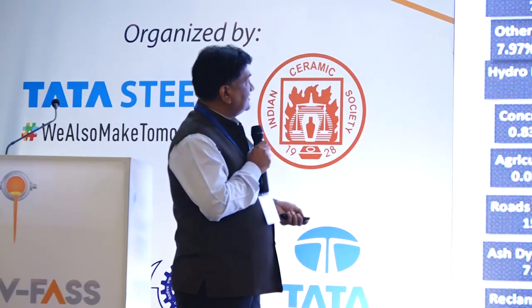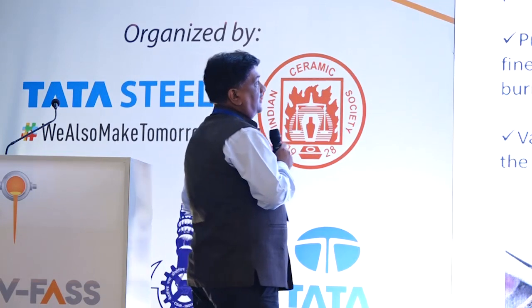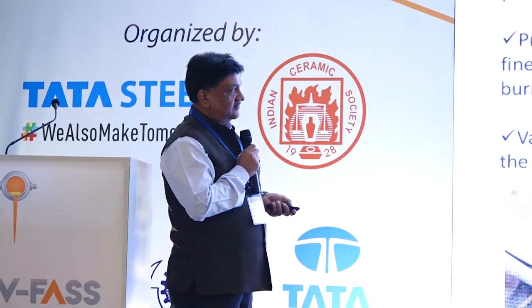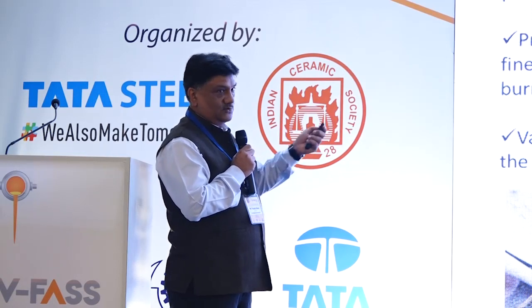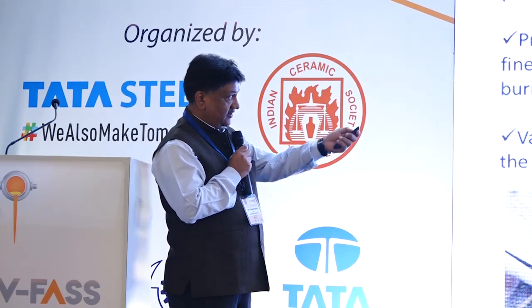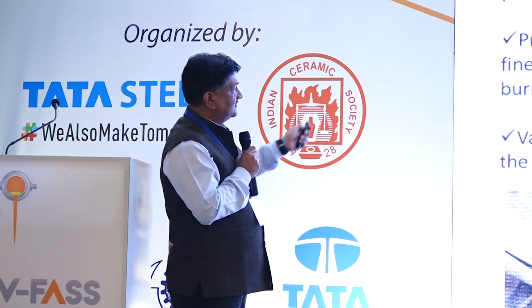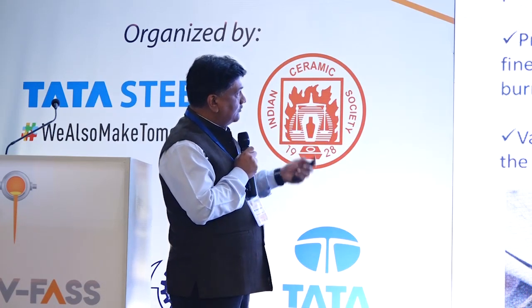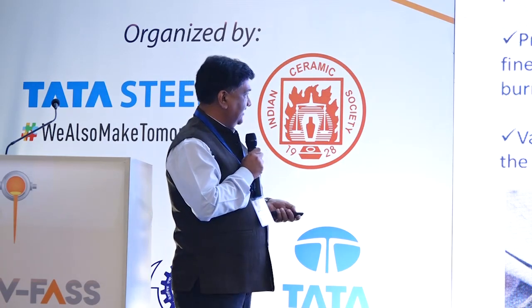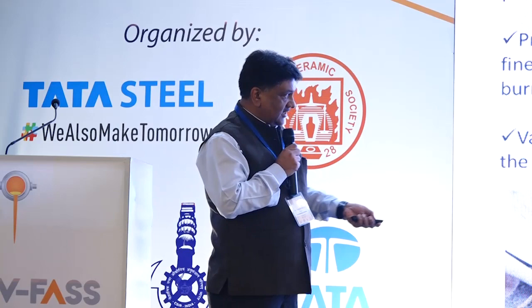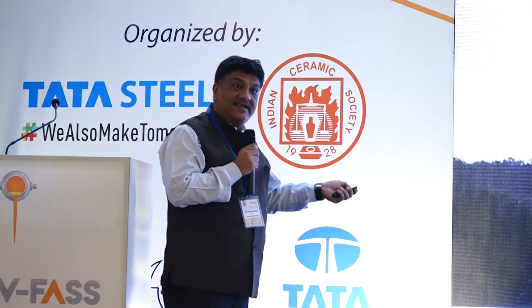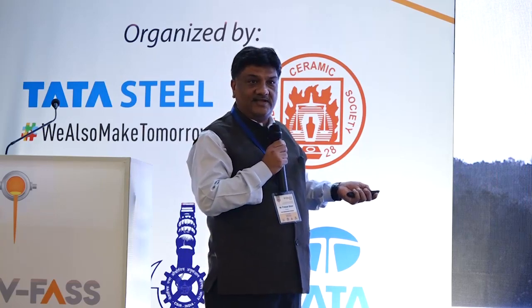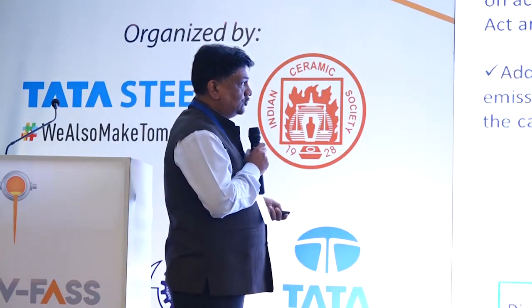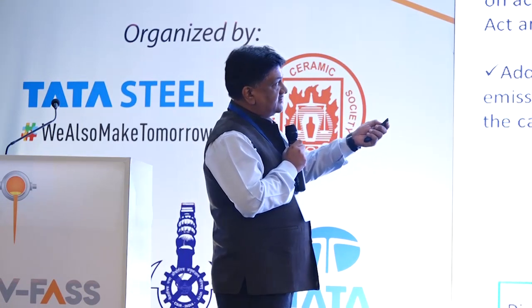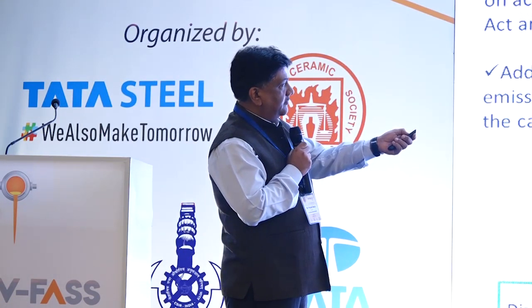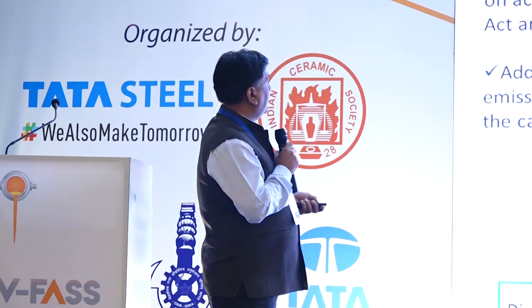So these are statistics on Indian industry. What majorly affects utilization of this combustion product? Of course, the sulfur, free lime, which has been talked about, unburned carbon, and gradation and collection process. So this is a function of all these factors which is affecting more utilization of such combustion product like fly ash. I would like to focus more on this unburned carbon element, which is there in coarse fly ash. So we are not using coarse fly ash or pond ash, but we made an attempt to use that. The certain limitations which codal compliances demand is that your LOI should be less than or equal to 5%.